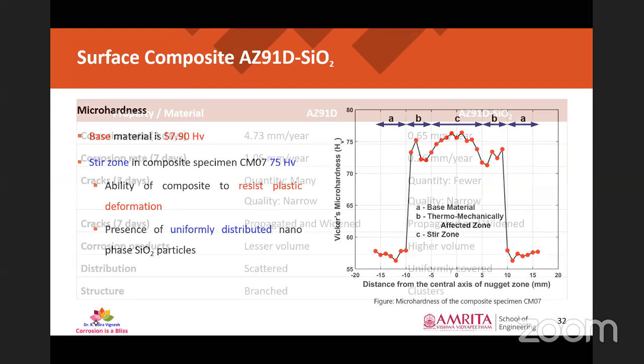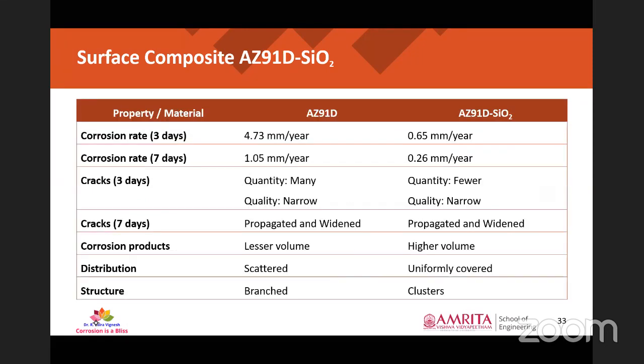Now from the corrosion perspective. When we compare the corrosion rate of the normal alloy and the composite, the composite had an average corrosion rate of 0.65 mm per year after 3 days of immersion, and after 7 days of immersion, the corrosion rate has reduced to around 0.26 mm per year. When we observed the surface morphology under scanning electron microscope, we observed that the number of cracks present in the composite is fewer than that of the conventional base material, and the cracks were very narrow with respect to the base material too.